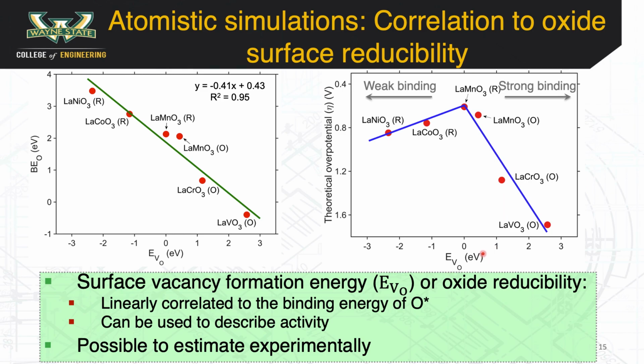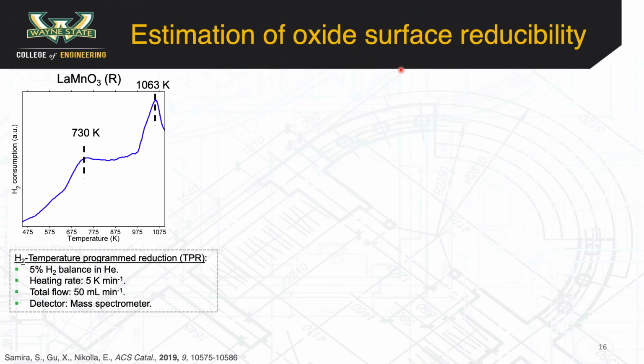One of the good things about surface oxygen vacancy formation energy or the oxide surface reducibility is the fact that it is possible to estimate it experimentally. One way to estimate the oxide surface reducibility is via hydrogen temperature programmed reduction. In a typical H2 TPR experiment, a certain mass of catalyst is loaded in a reactor under the flow of a reductant such as hydrogen balanced with helium.